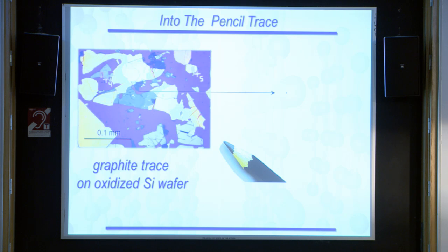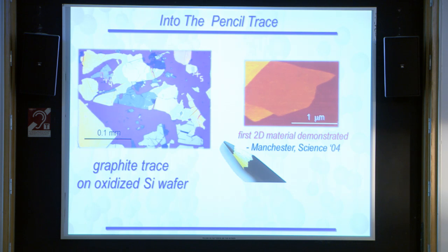Those whitish are the thickest ones, and then the light blue, and then blue and purple are the darker ones. The more purple it becomes, the thinner it is, and those which you practically cannot see are exactly the monolayers. Well, at first it took us quite a bit of searching through those crystals. Our first samples were quite small, just about a micrometer large, but it's already enough for our nanotechnology fabrication technique to produce certain meaningful devices out of it.